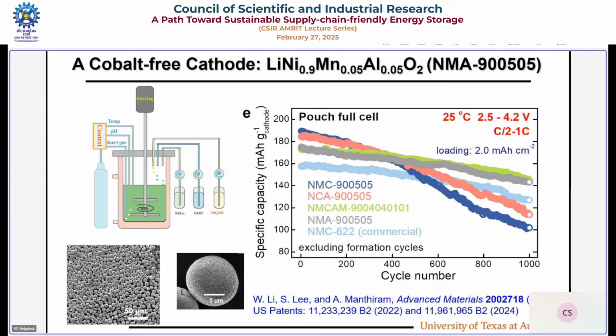So we make all our materials in our lab. Sometimes I was in Calcutta many times. Can I make nano materials, all these layered oxides, I can use it? Nano is a bad word for battery community. You have to use nano only if something is not working. Lithium iron phosphate, if it is not nano, it won't work because it's the worst insulator, worst ionic conductor. You have to make it nano and coat with carbon to overcome that challenge.